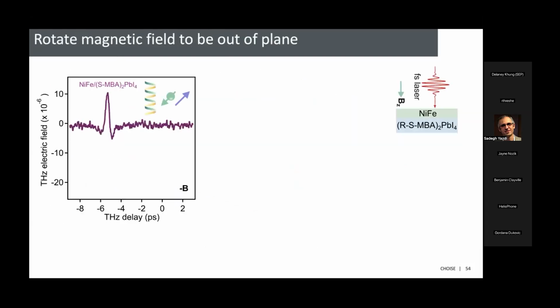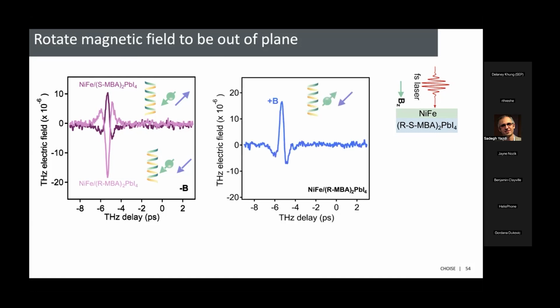Okay. So one chirality, one polarization, the spin goes up, or the charge current goes up, and then you change the chirality, but keep the polarization the same, and it goes down. You can also change the magnetic field and you get reversal of the charge current.